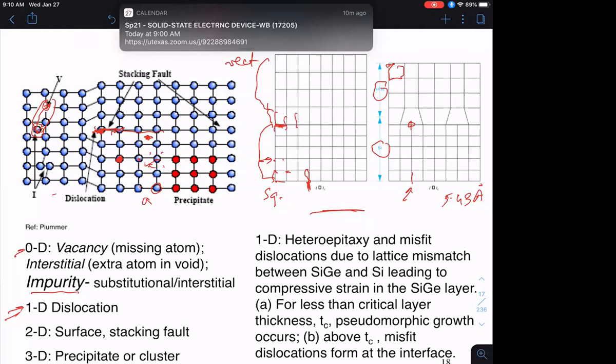And if you take a square or a cube and you squash it in the XY plane, it would get elongated in the Z direction. I'm calling this the Z direction, and these are the XY directions, okay? So I take the cube or the square, squash it in the XY plane, it gets elongated in the Z direction. And that's why you end up getting a rectangular lattice in this cartoon view on the left-hand side, okay? Now that introduces mechanical strain in the layer of silicon germanium, because then I have to squash it to fit the planes with respect to the underlying silicon planes.